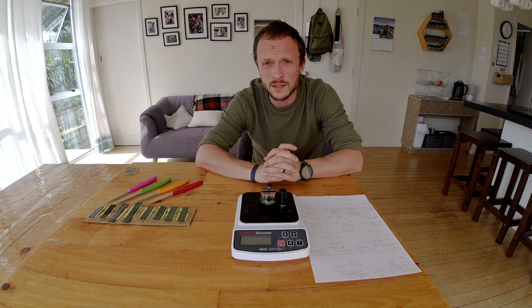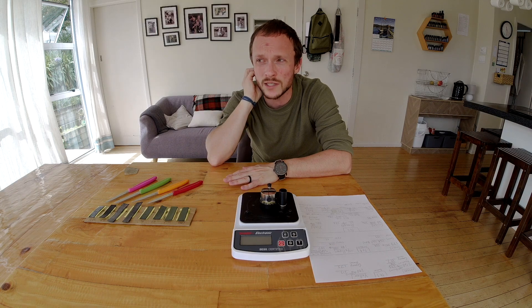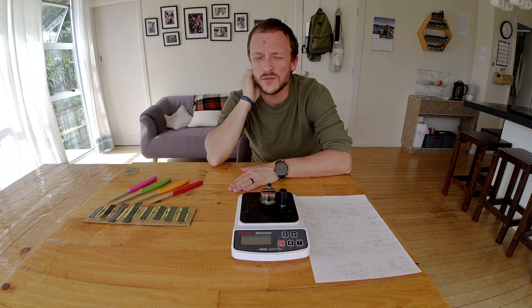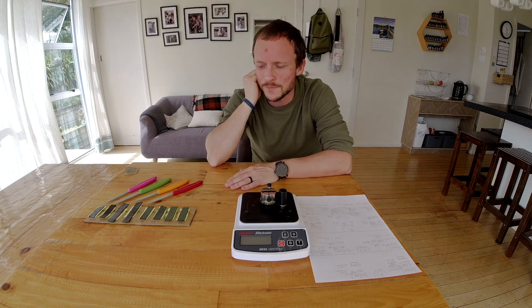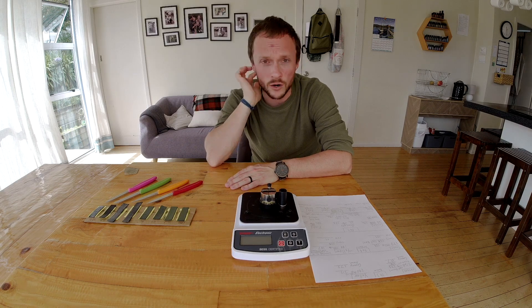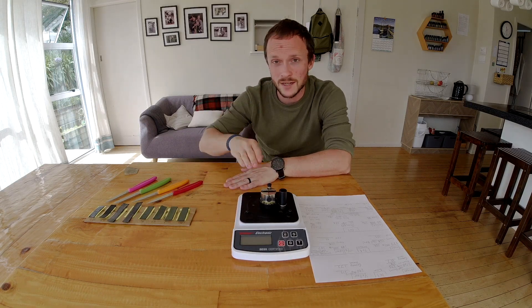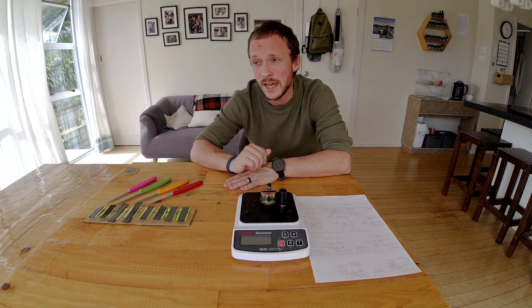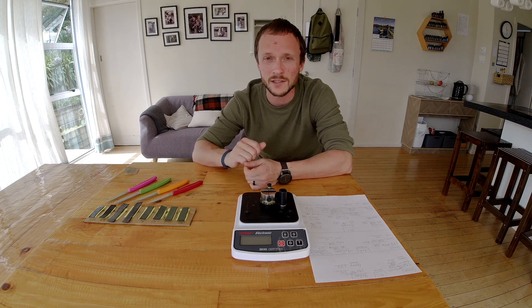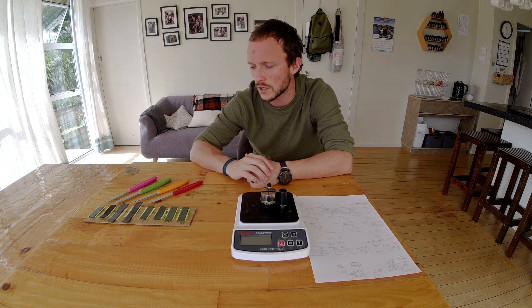I'm incorporating some things I learned in past tests. At least with my stropping technique, I've been finding that around 10 strokes really shows you the effect of the strop. If you go more than that — like 15 strokes on each side — and your abrasive is really hard, like diamond, there can be an effect where the best number actually goes back up because you formed a bit of foil burr. I found that out by doing that and then seeing the number drop pretty dramatically when I put it on the rough side of an unloaded kangaroo strop, which seemed to strip a little bit of foil burr off.